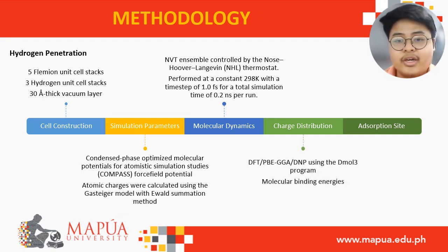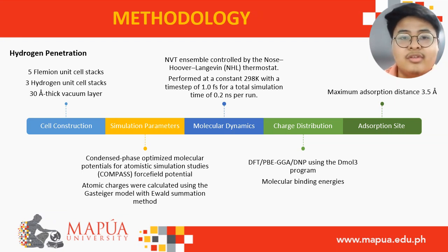For the charge distribution, we made use of the DFT, PBE, GGA, DNP under the DMol3 module. Here, we were able to evaluate the molecular binding energies of hydrogen to the side chain. Lastly, for adsorption site, a maximum adsorption distance of 3.5 angstroms was set.